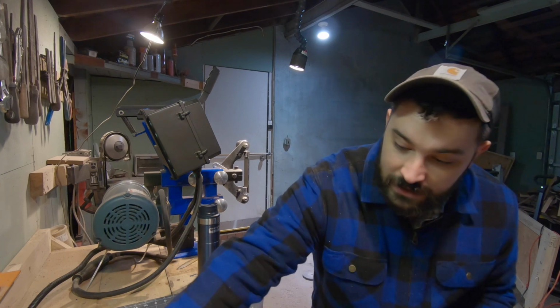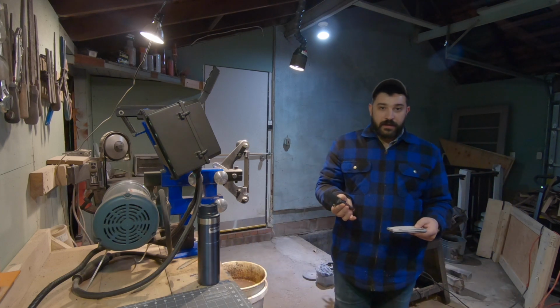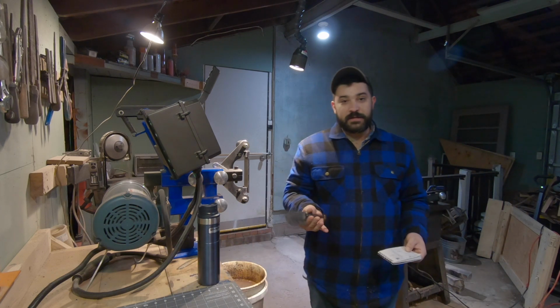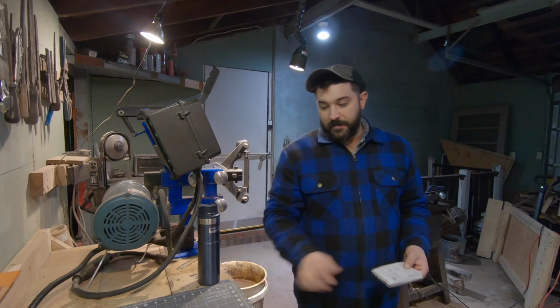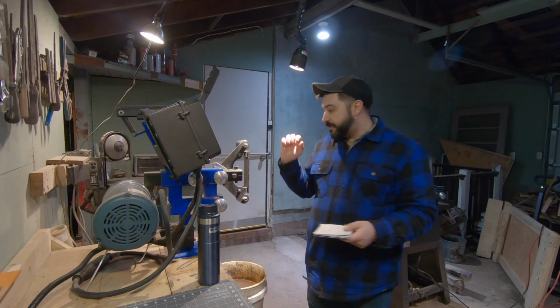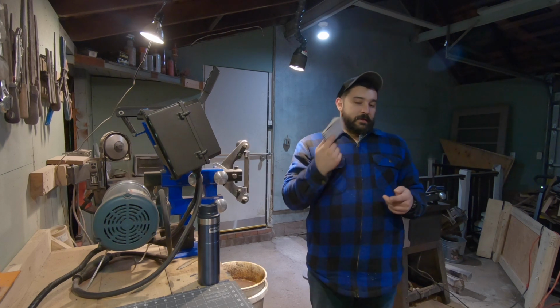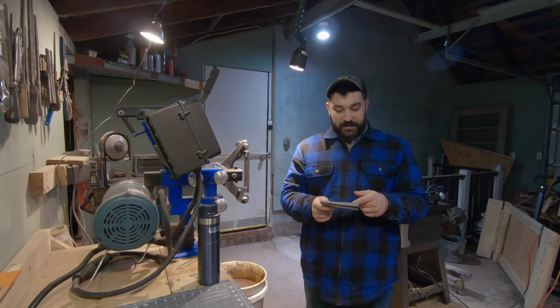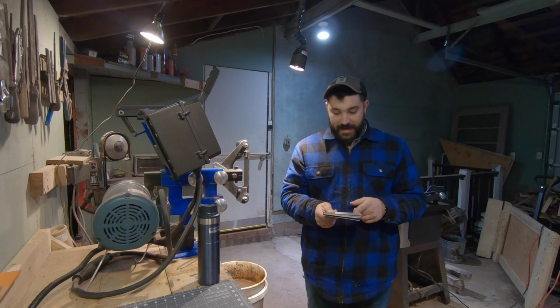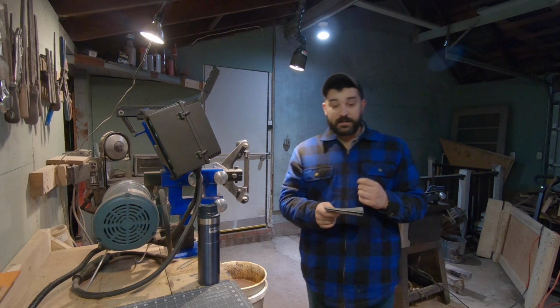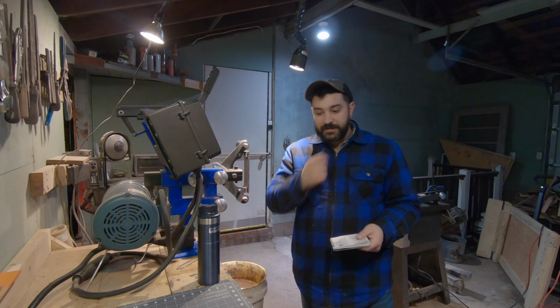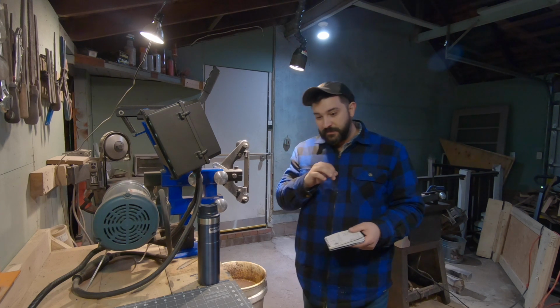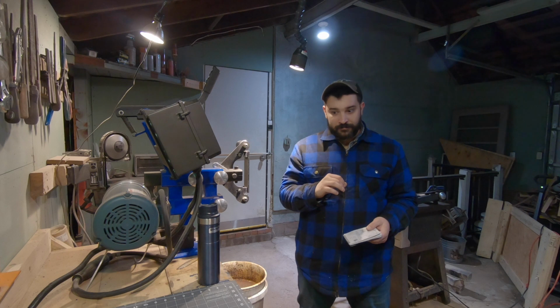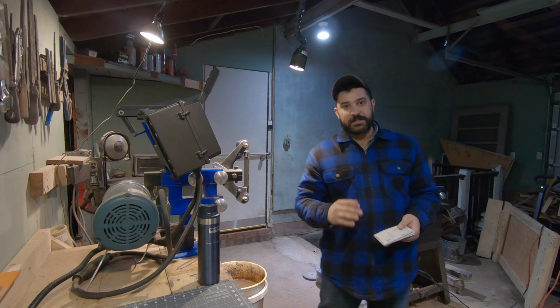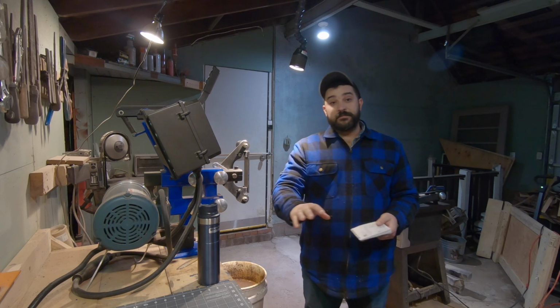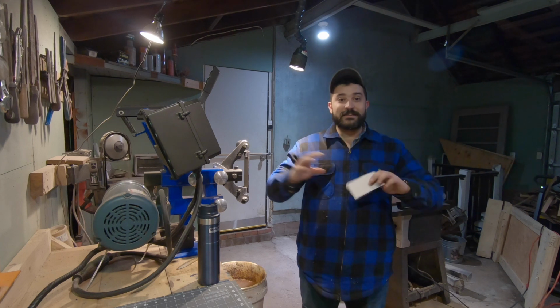The LT Wright 3V. I know this is softer. I wish I knew the HRC on this. It just felt soft sharpening. It felt soft grinding. The initial was 70 passes times 2, which is 140 cuts. Not the greatest. Also, there's not a lot of carbide formers in 3V, so we don't get that wear resistance, but we do get that toughness. That's a very tough steel.